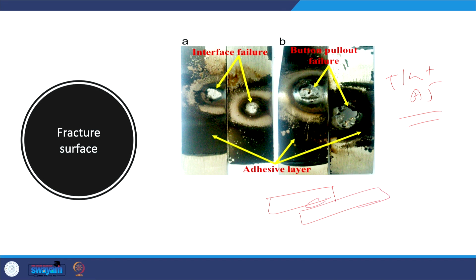So, here if the failure occurs like this, then this is interface failure. Or if the button is pulled out from one of the sheets, then that is known as button pullout failure, and the pull out failure contributes towards the strength in a much better way as compared to simple interfacial failure. What is important to see is that around the zone wherever the TIG spot is made, a black zone is formed, due to the thermal decomposition or thermal damage of the adhesive, but around that our adhesive will be contributing in a good way towards the external load.